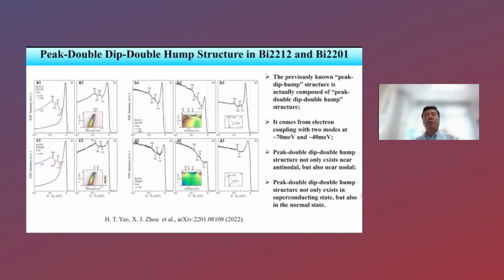So eventually, I'll come down to the famous peak-dip-hump structure. For a long time, people thought that in Bi2212, near the antinodal region in superconducting states, you see the peak-dip-hump structure, usually one peak, one dip, one hump. But by our laser ARPES measurements, with very careful inspection, it's not one peak, one dip, one hump. It's a two-dip, two-hump structure.